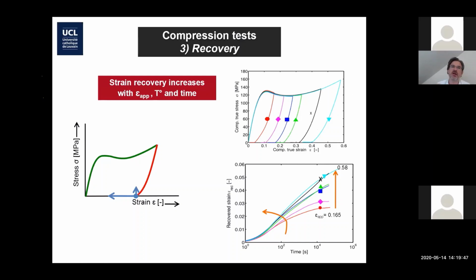This is now entering more specific questions that we addressed. Upon unloading, you see here compression tests that have been unloaded, and we monitor the unloading as well as the recovery. You see the recovery below when the stress is 0. And this is the curve showing you the strain that is recovered when the stress gets down to 0 as a function of the strain that was applied before. So if you apply 60% strain and then you unload, you recover typically 2–3%. After you have, of course, recovered another part of the deformation, you're getting almost to 0.